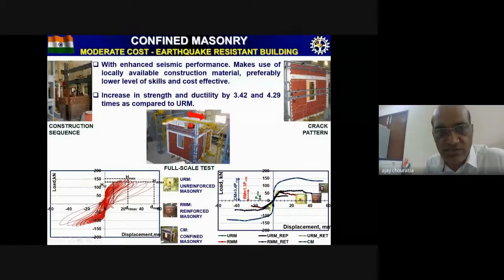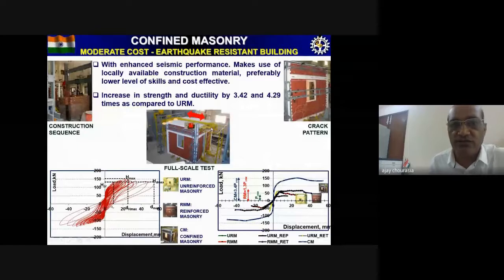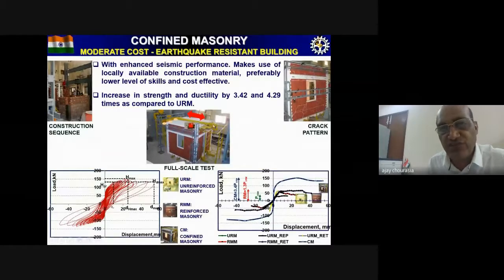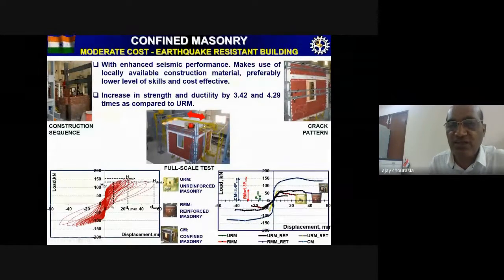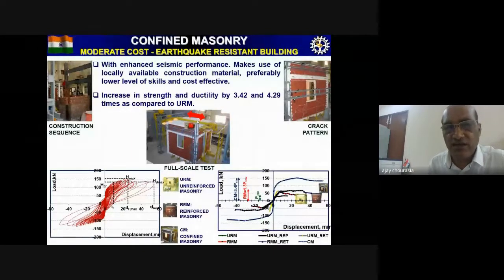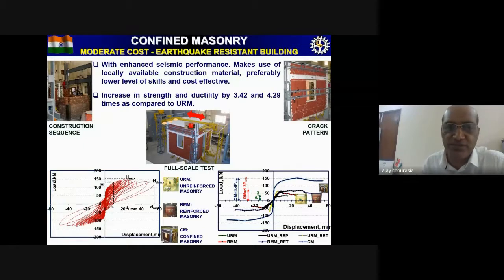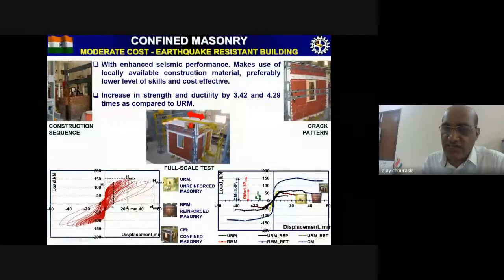Upon construction of this model, lateral incremental loading was applied at the roof level. The full-scale test was carried out under displacement-controlled reverse cyclic loading, created by attaching the actuator at the roof level. The load from the actuator was distributed uniformly at 8 different locations on either side to achieve the cyclic action. To measure the response of the test structure, we provided strain gauges and LVDTs at different locations, and the displacement and load were also measured by the actuator. Upon conducting the tests, the data was analyzed and the results were assimilated and presented in the typical style to understand the seismic performance of the confined masonry.